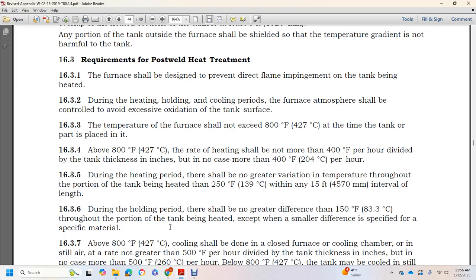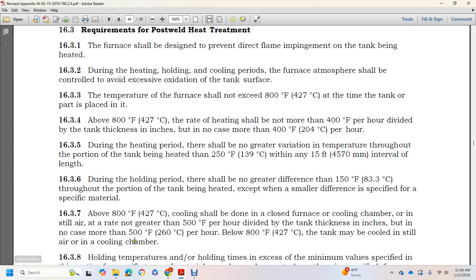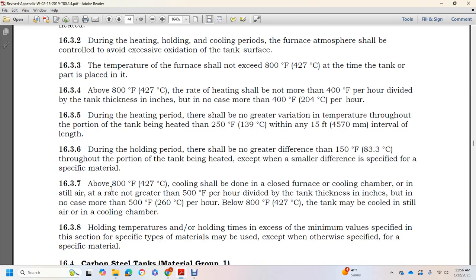During the heating period, there should be no greater variation in temperature than 250 degrees Fahrenheit throughout the portion of the tank being heated within any 15 feet of interval length. During the holding period, there should be no greater difference than 150 degrees Fahrenheit throughout the portion of the tank being heated, except for a smaller difference specified for the specific material.